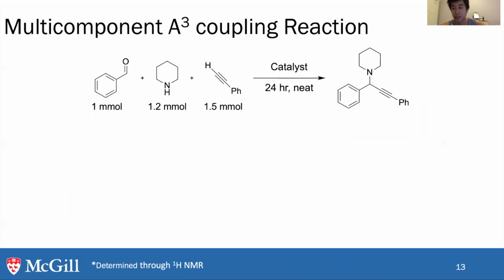So off this, we tried to investigate another reaction, and we picked the aldehyde-amine-alkyne coupling reaction, due to the fact that it's regarded in the literature that it's not gold(0) that catalyzes it, but in fact the gold(I)/(III) redox cycle, such that oxidative addition and reductive elimination can occur. And so for our case, with gold(I) being the predominant species, this would be a really nice reaction to further validate that.